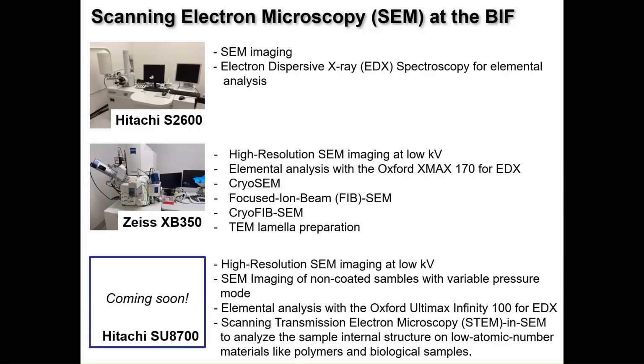In the coming months, we are going to install the Hitachi SU8700. This is another SEM. We can do high resolution SEM imaging at low kV. Also, it has a variable pressure mode. So we tested some non-coated samples, and we can get a very good high resolution image using variable pressure